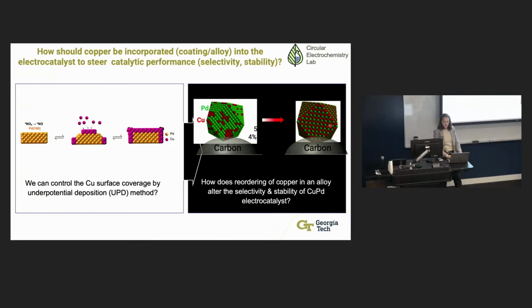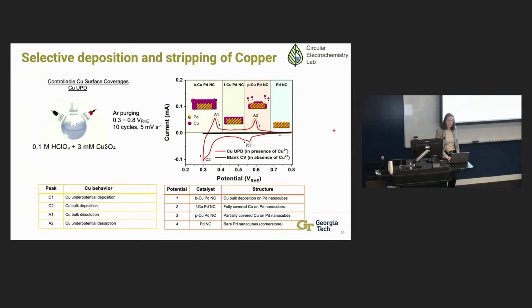And then the other thing that we looked at was basically creating these alloys that were ordered. If you create them as a very well-ordered alloy, the atoms are not likely to move, and so you might have more precise catalysis. And so we looked at these different ways of making copper palladium nanocrystals.